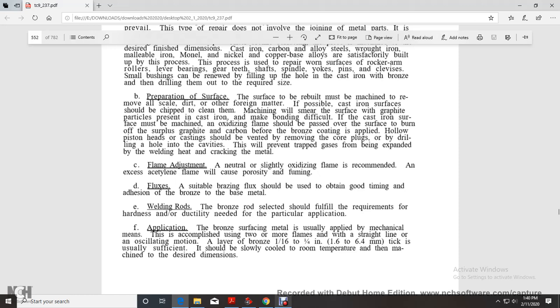Alright, preparation of the surface to be rebuilt: machine to remove all scale, dirt, and other foreign material. The cast iron surface should be cleaned thoroughly. Machining will smear the surface with graphite, particularly in the presence of cast iron, making bonding difficult. The cast iron surface must be machined, and an oxidizing flame should be passed over the surface to burn off surplus graphite and carbon before the bronze coating is applied.